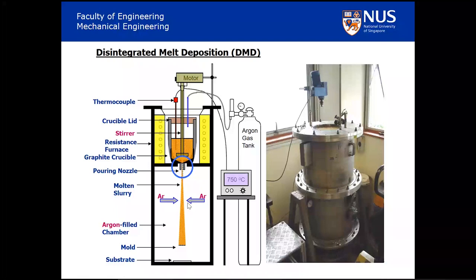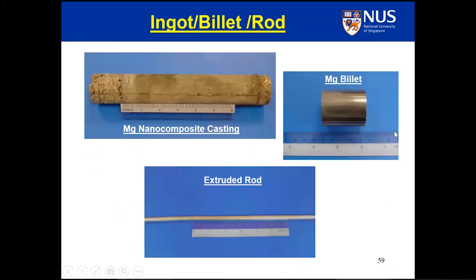A typical facility that we use is shown here, and it is actually very cheap. Anyone can do that. You can get the ingot like that, machine it into a billet, and extrude it into a rod. We have also upscaled this technique to 20 kg. But magnesium being very light, 20 kg means you can get a 5 foot high billet, maybe about a foot in diameter. So it's very big for the industrial level.